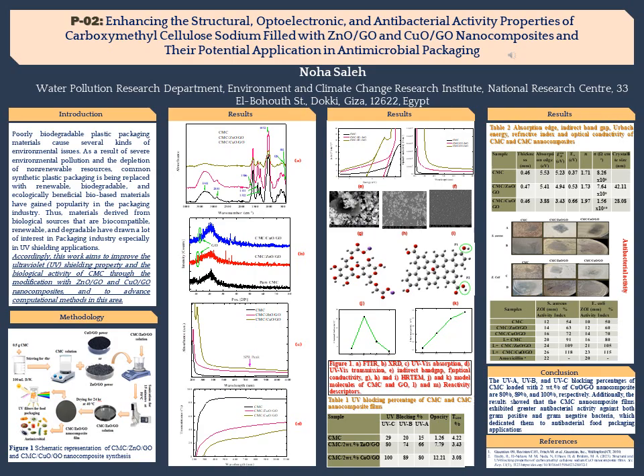Total dipole moment, frontier molecular orbitals, chemical reactivity descriptors, and molecular electrostatic potential maps were all studied using the B3LYP, LANL2DZ model. The total dipole moment and frontier molecular orbitals investigations revealed that the CMC, copper oxide, graphene oxide model has the highest total dipole moment and the smallest band gap energy. Moreover, CMC's reactivity increased after copper oxide, graphene oxide nanocomposites integration, as demonstrated by molecular electrostatic potential mapping.